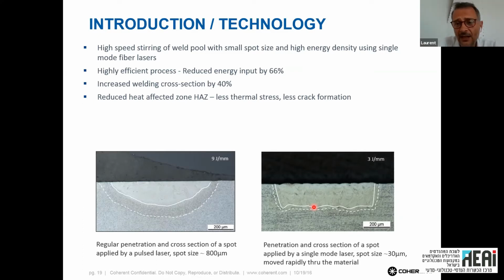So in a lot of cases, it's an advantage. Another advantage is less power, because I'm working with 30 micron and going quite fast inside the material, so I can use much less power. This is also the reason why I'm able to decrease the heat affected zone. With all of these parameters under control, I have a very, very stable weld. And because it's comparable, this weld is now qualified for this medical application, because we are really close in terms of welding seams.